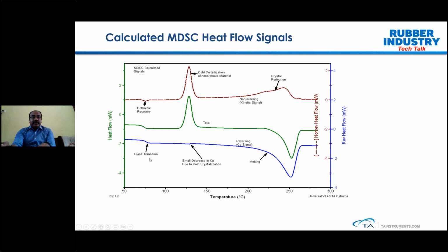What is glass transition temperature, melting point. So these are the thermodynamic events which are easily measurable. Another is the non-reversible signal, which shows all the kinetic events. You can even see a small endothermic peak occurring close to the glass transition, which is because of an enthalpic recovery, followed by the crystallization and then crystal perfection.